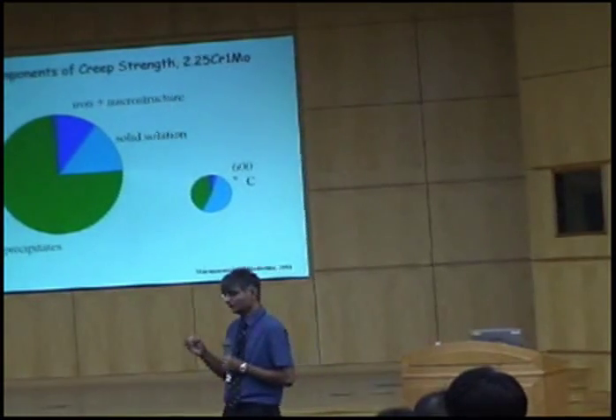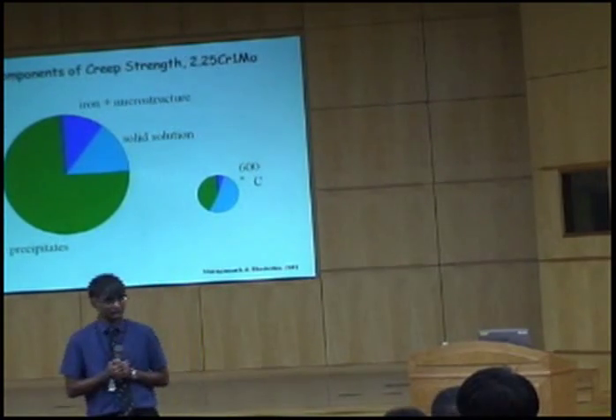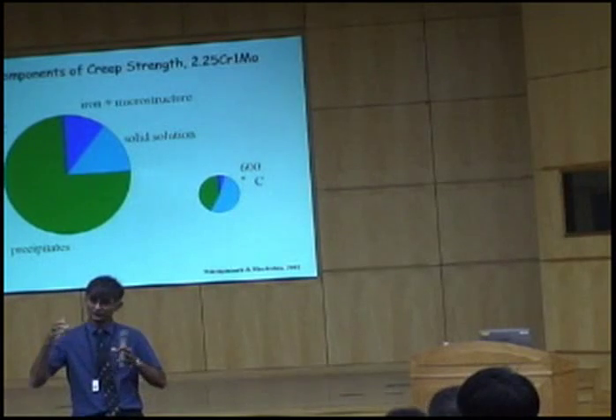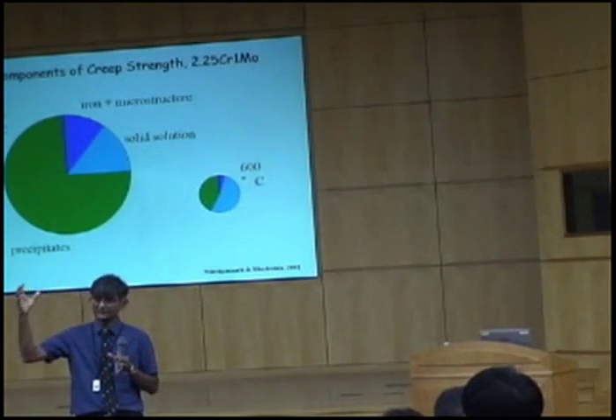So there is a great deal of research, including at POSCO special steels, to design creep-resistant steels for high temperatures. And the focus there should be on solid solution strengthening, because we are going to put these steels into service for something like 25 years. You cannot rely on precipitation hardening. Those precipitates will coarsen and you quickly lose precipitation strengthening. Solid solution strengthening is the way to go for creep resistance at very high temperatures, from 600 to 650 degrees centigrade.